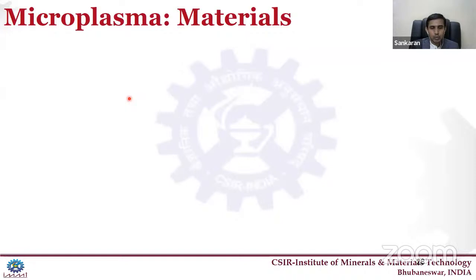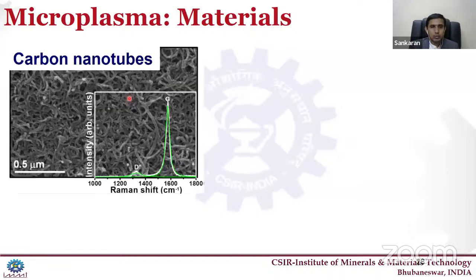So far I have shown how to characterize a microplasma device when you're talking about a cathode material. So what are the materials people have used so far? People have used copper, molybdenum, and then zinc oxide and other oxide based materials. But those materials cannot withstand for a longer time, and they need a high breakdown voltage. They need a high applied voltage, more than 600 or 700 volts. Then we need to consume more energy. So then people started to work on carbon based materials, because carbon nanotubes and graphene have a turn on field in field electron emission of less than 1 volt per micrometer. So you can see carbon nanotubes is a very good field electron emission based material.